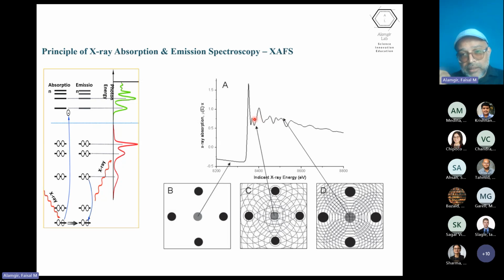So the interesting thing here is that we have atomic structure embedded in the absorption spectrum, but it requires you to scan over a wide energy range in order to get a clear picture of that atomic structure. So this is a challenge of the extended fine structure measurement, that it necessarily is a wider band of information, and therefore often that also means that it takes longer to measure.